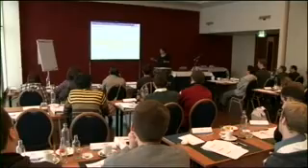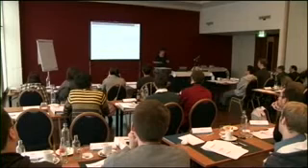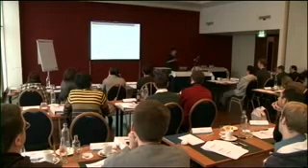I'm sorry, but I haven't got time to discuss all the mechanisms behind these different stages. From a practical point of view, it's very important, because the fact that it slows down and then speeds up means you've got time to make your concrete, transport it to the building site, and put it in the form before it starts setting. If you didn't have this slow down before it restarts, you would never be able to use concrete in a practical sense, because it would just stiffen immediately when you added the water.